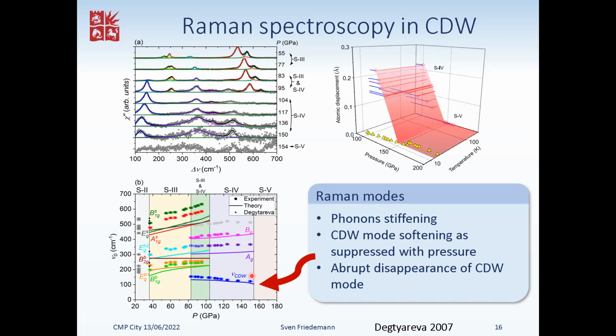And this is exactly what you might expect for the charge density wave, because it has been figured out earlier by X-rays that the atomic displacement reduces as you get to higher and higher pressures. So essentially this traces the strength of the charge density wave ordering parameter, and hence the curvature of the potential, and hence the Higgs mode or the amplitude mode of the charge density wave. But what's most noticeable is that it doesn't go to zero, rather it abruptly disappears at the critical pressure.